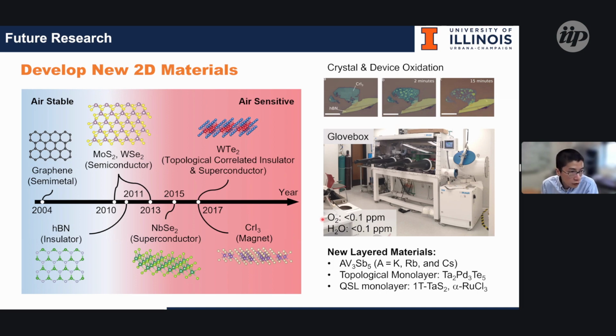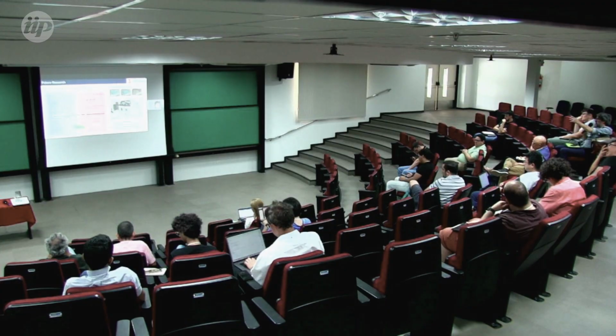What I want to also note here is that we have been developing some spectroscopy methods in collaboration with Oak Ridge National Lab. We are trying to fabricate these devices to be encapsulated with hBN, and with this method, if we can shine light into the system, we can study their high energy spectrum and understand excitation or excitons coming from the system. With this, we could have some interpretation of how the single electron band or how the correlated band forms in such a system.